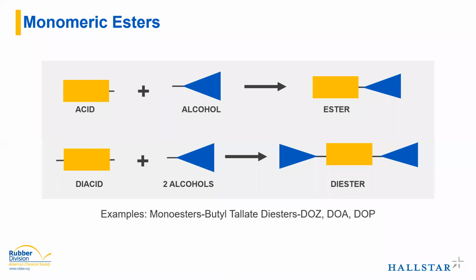On the bottom, to make a diester, something like DOZ, DOA, DOP, we have a difunctional acid that has 2 acid groups, 1 on each end of the molecule, and we use 2 monofunctional alcohols, similar to in the monoester, and each one reacts with 1 of the acid groups to give a diester with 2 ester groups.